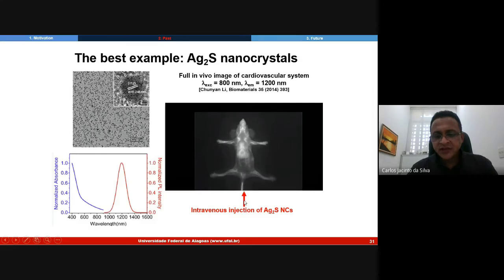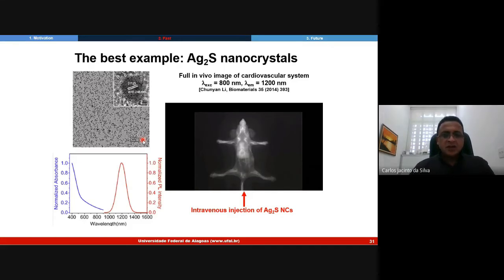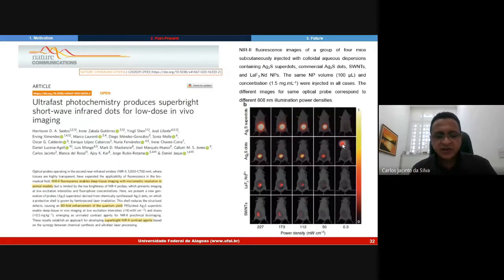Introduce the silver sulfide in this part of the mice and the distribution in the organs. Using the same material, silver sulfide, we are able to increase its luminescence quantum yield by 80 times using this: ultra-fast photochemistry by means of an impulsed intense laser. Again, this material emits in the second biological infrared window, and it was called superdot.